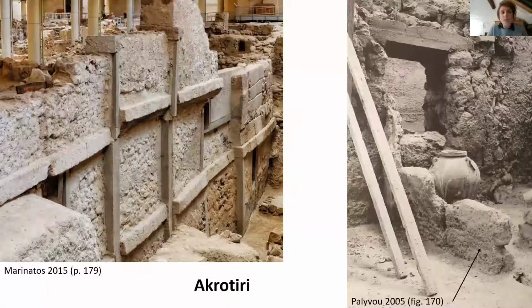Another reason why mudbricks are often neglected from Minoan architectural studies is that the best preserved site of the Bronze Age Aegean, Akrotiri on the island of Thera, shows only rare instances of mudbrick use. Buildings in Akrotiri are preserved up to several floors high, but they are chiefly made of stones, and mudbricks only appear there in the form of upright standing elements forming beams or parapet. So Minoan archaeologists, who often refer to Akrotiri for in situ architectural comparisons, find little evidence pertaining to mudbrick on this site.